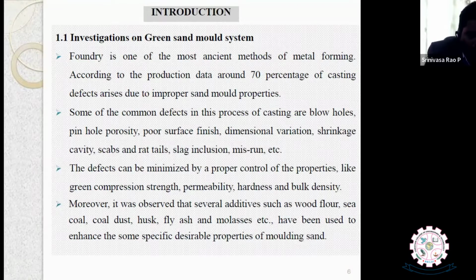Let me give you a brief introduction about the green sand mold system. Foundry is one of the ancient methods in metal forming. According to the production data available, 70% of casting defects arise due to sand mold properties. That means if you are able to improve the properties of the sand mold, then automatically you will get good strength in the casting. Most of the common defects we find in these castings are porosity, which is the major problem, very poor surface finish, dimensional variation, shrinkage, cavity, scabs, rat tails.